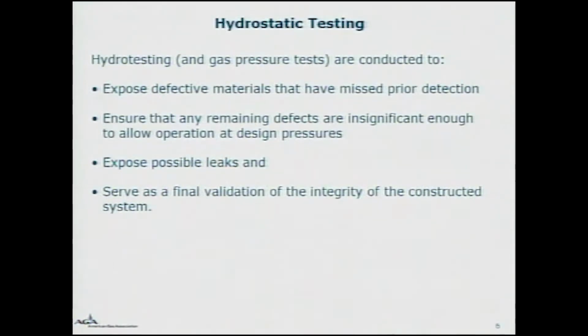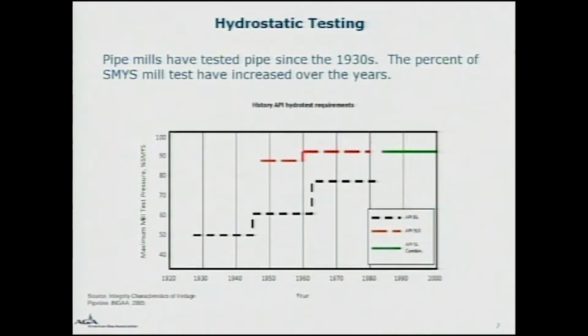Hydrostatic pressure testing is a standard practice now done by operators as a post-construction, pre-commissioning strength test for the as-constructed facility. It serves as a final validation of the integrity of the constructed system. Hydrostatic mill pressure tests are performed at the pipe manufacturer at pressures now significantly higher than operational pressures. This chart, taken from API 5L, the INGAA 2005 report, shows maximum test pressures for large diameter pipe increasing from 50% of specified minimum yield in 1928 to 90% of specified minimum yield in 1983 when the API 5L and 5LX specifications were combined.